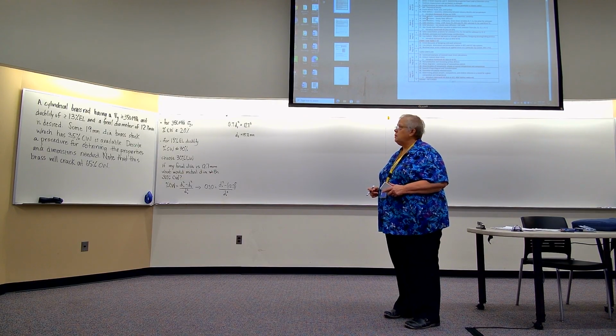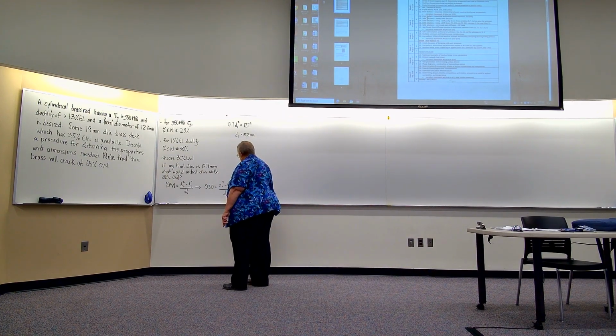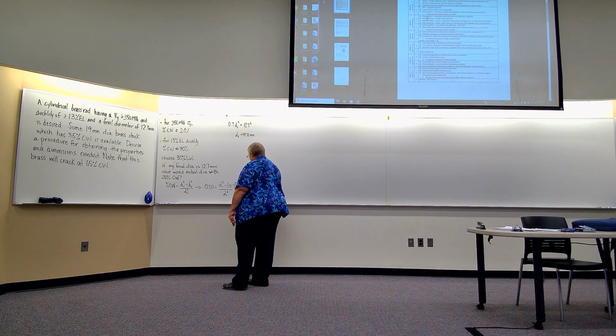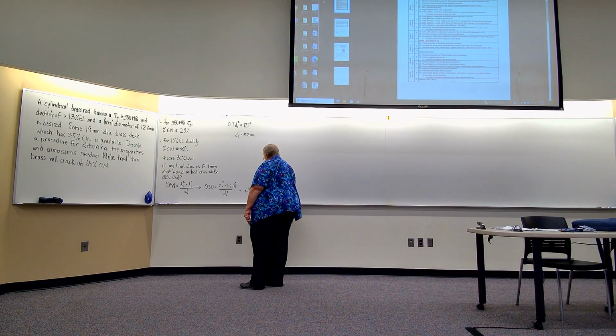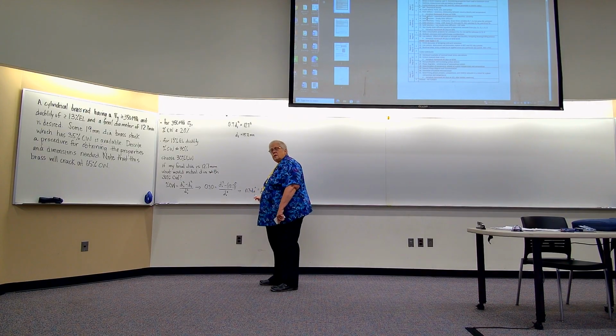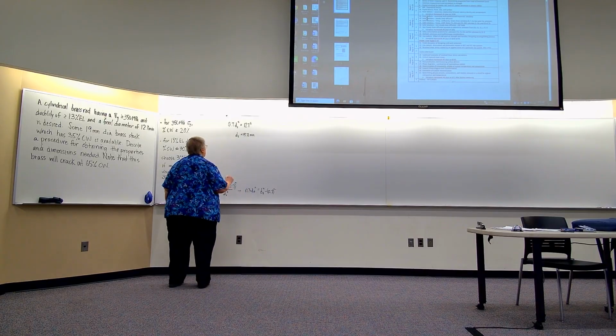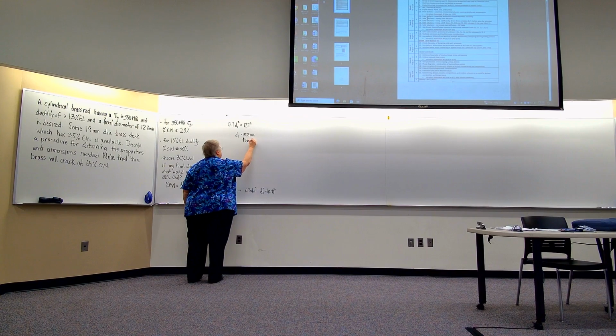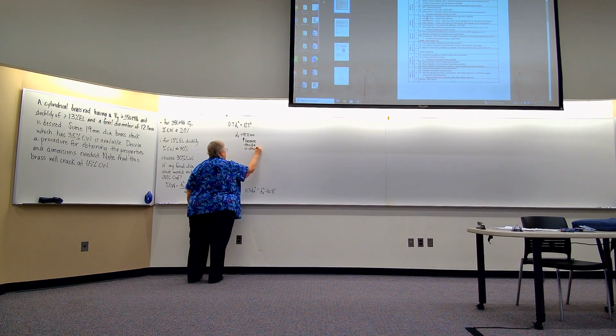Olivia: Why is it 0.7? So this is 0.3 d0 squared is equal to d0 squared minus 12.7 squared. So essentially it's 1 minus 0.3, which is 0.7. Okay, so because this diameter is smaller than 19 millimeters, this process has to be conducted in more than one step.